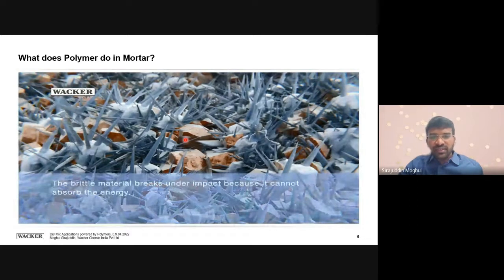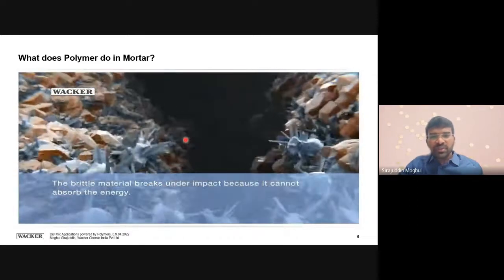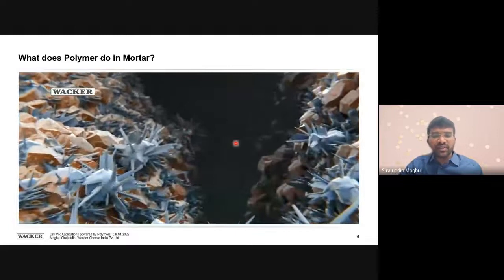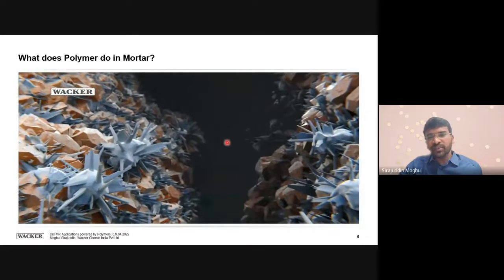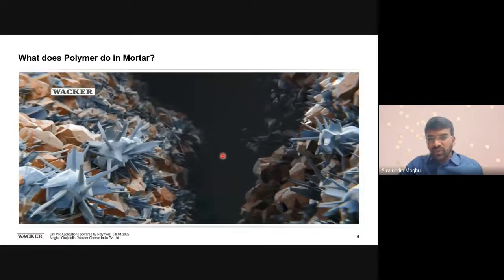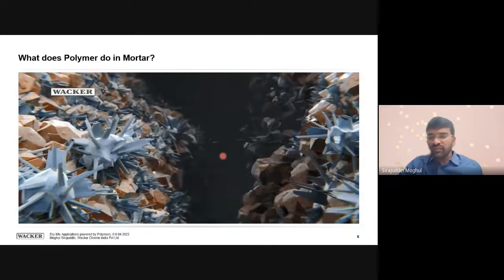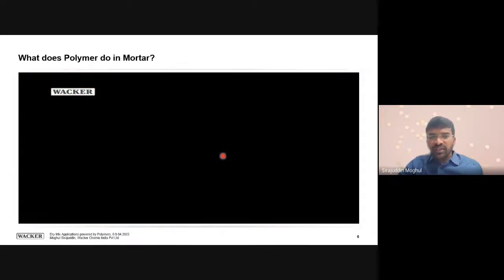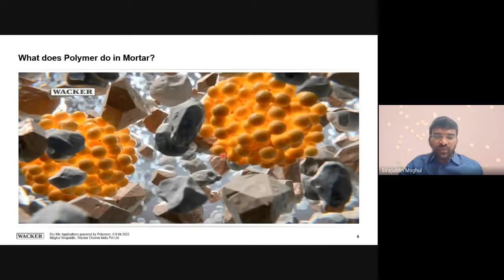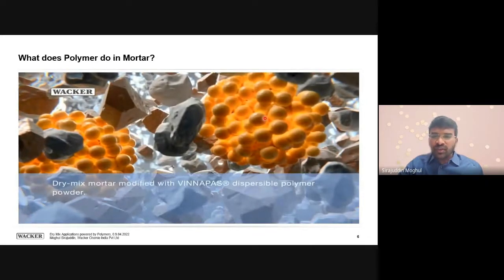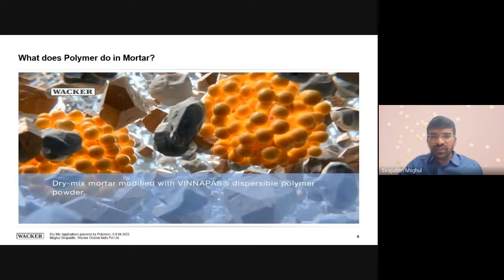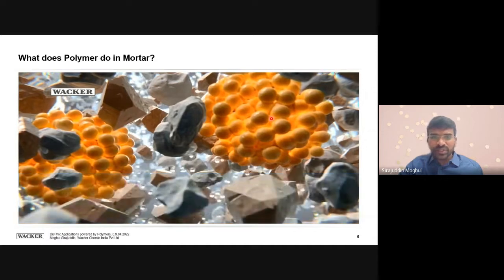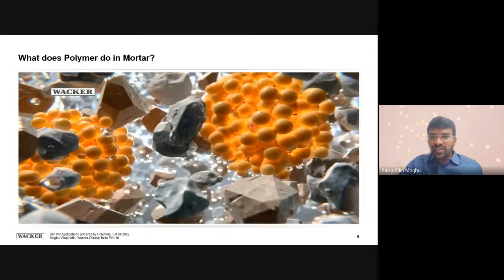And when it is only cement mortar, whenever there are stresses, the matrix is very brittle, and then it cracks and then it breaks. So this is what usually happens if it is not modified with polymer, and this is why you see a lot of cracks. In a similar formulation, now the orange color, or the yellow color, I don't know exactly how it is visible to you all there, this is a polymer.